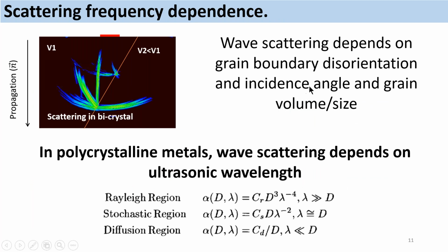So if we look into the literature, we will see that the attenuation due to scattering by grains is usually written as grain size to the power of an exponent times the wavelength to the power of an exponent. Wavelength is simply the inverse of the frequency. So you see here, depending on the frequency and the grain size, you will have a different relationship between the attenuation and the frequency. And so we usually talk about regimes of scattering. In metals, we are mainly interested in 2 regimes, the Rayleigh region and the stochastic region. And mostly, to simplify things, we can assume that we are usually in one single regime, and construct those calibrations this way.